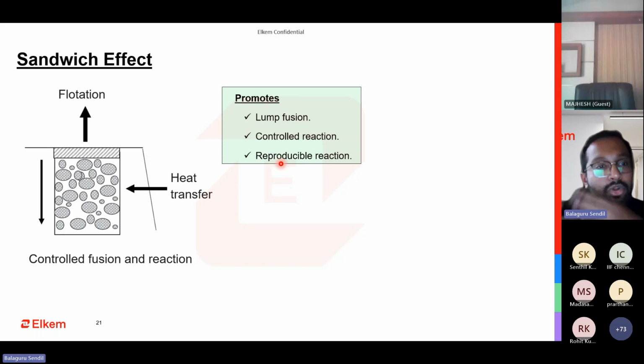This needs to keep producing. This will start melting here. This will again start melting here. So this reaction keeps happening continuously so that more of the metal that you have in the ladle gets exposed to these reactions, and these reactions will form a very stable nuclei, and that nuclei with subsequent inoculation will give you a very good microstructure.